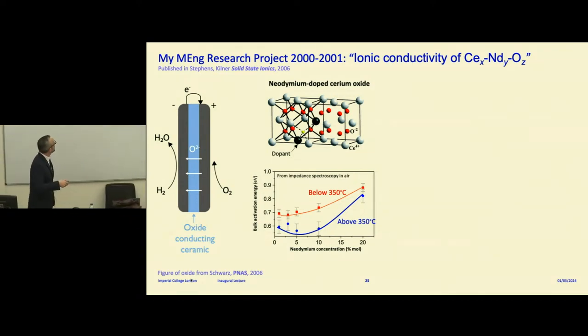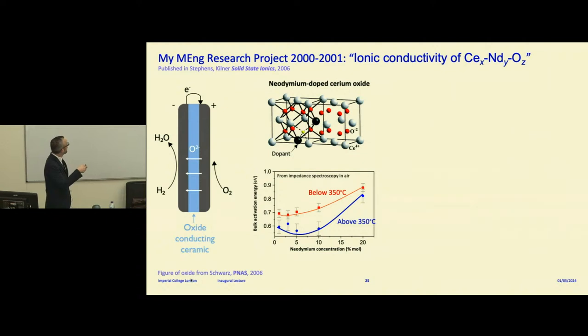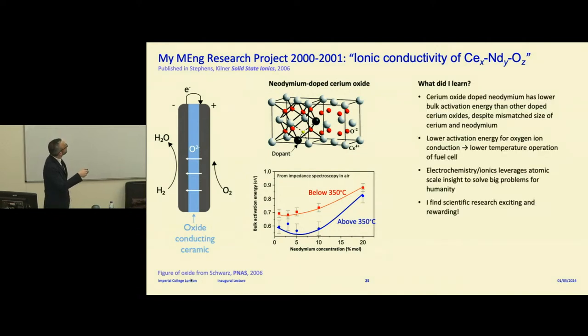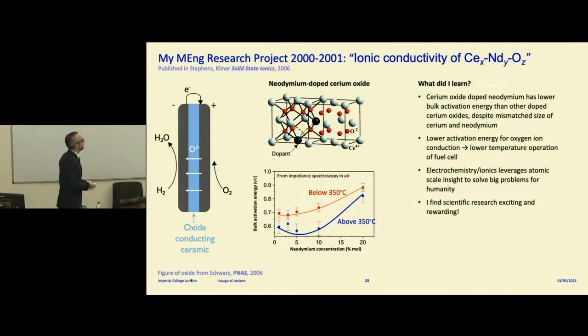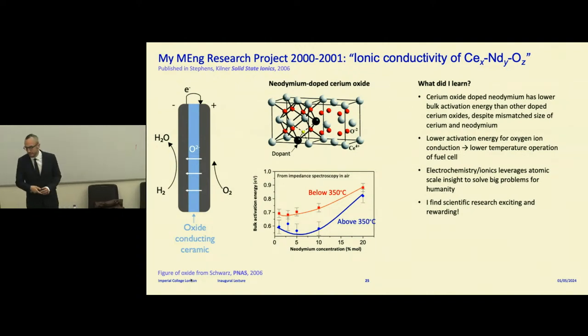What we found is that the activation energy was lower than what people had reported for any other materials. It was slightly counterintuitive, because neodymium has a slight size mismatch with cerium oxide, and people usually thought you need to minimize the size mismatch. So this is exciting for me.